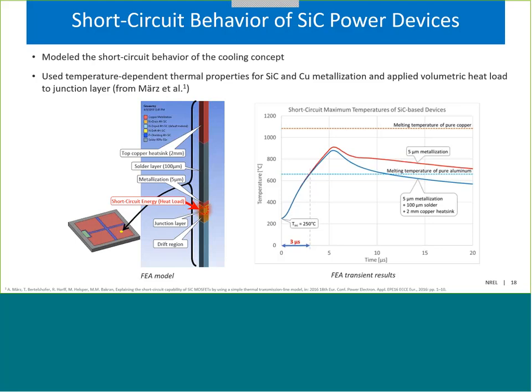The blue line represents the temperature response for the current design, where we have soldered a heat spreader to the top of the device, and then we're applying a heat transfer coefficient on top of that heat spreader to simulate cooling from the dielectric fluid. And so what our results show is that the current cooling strategy really has minimal effect in delaying the temperature rise at these microsecond timescales.